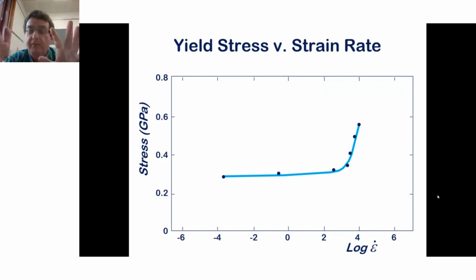So this graph shows that at 10 to the 3 and above, there's a big change in the yield stress of the material. What is a strain rate of 10 to the 3 in the real world? A strain rate of 10 to the 3 is two cars impacting one another on a road. It's a lower strain rate than a bullet hitting a window, but it's very similar. So these are impact events. These are explosions, dynamic loadings, blast waves.